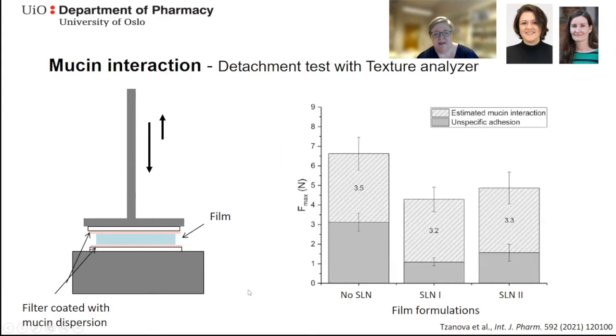Then we compared the films with respect to mucin interaction, and we used a very simple setup where we have mucin dispersion on filter papers, and we put the film in between, and then we measure the forces it takes to detach the mucin and the film.